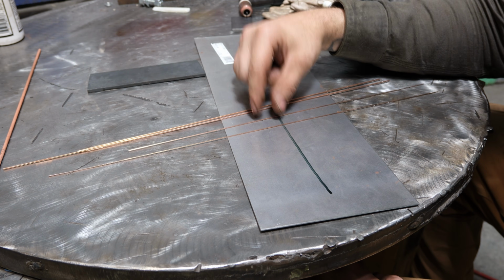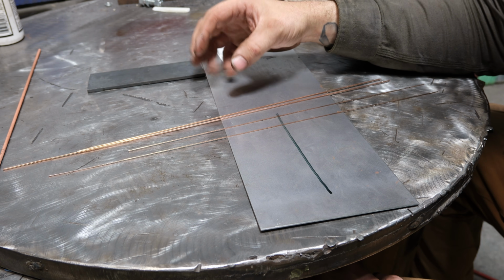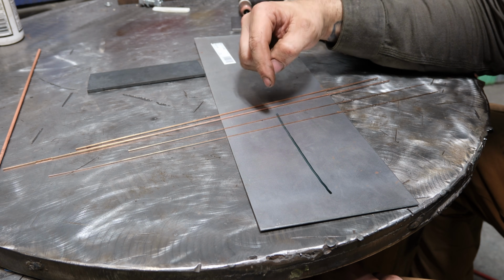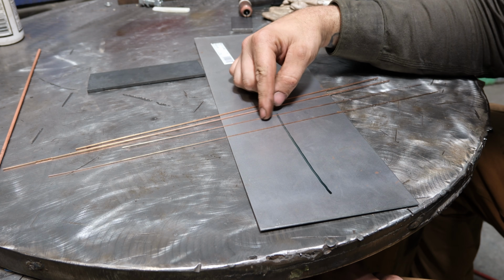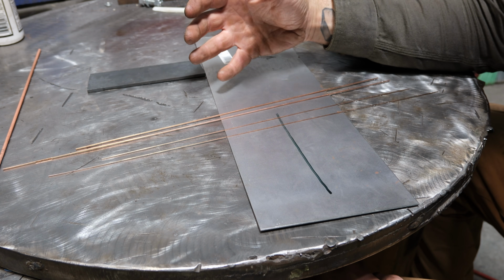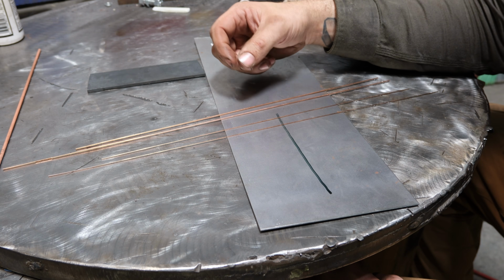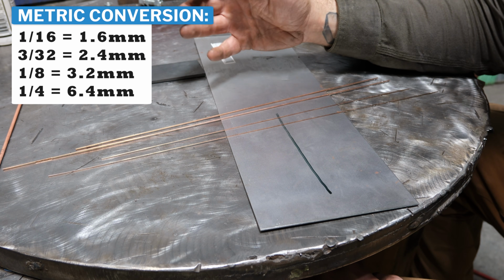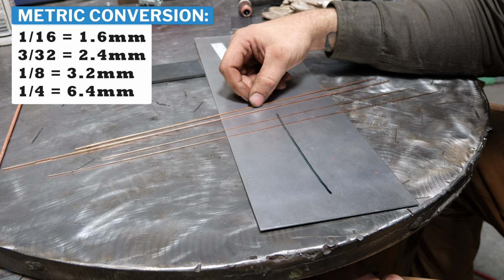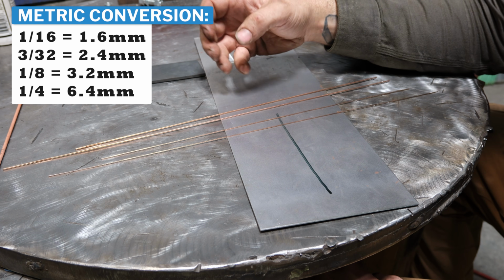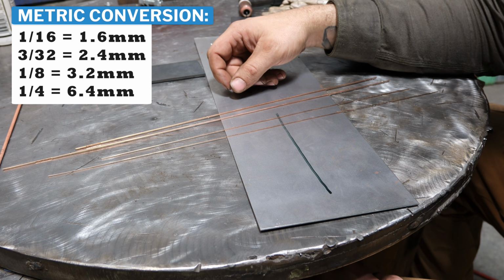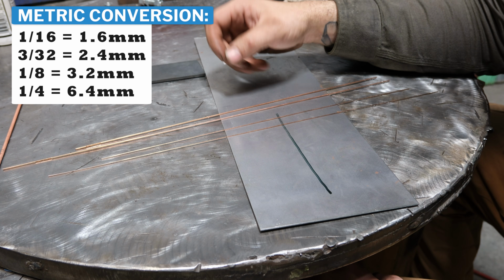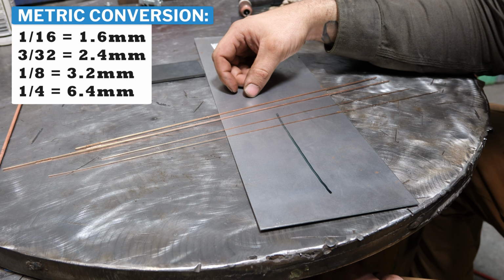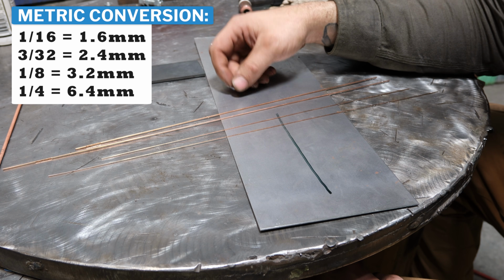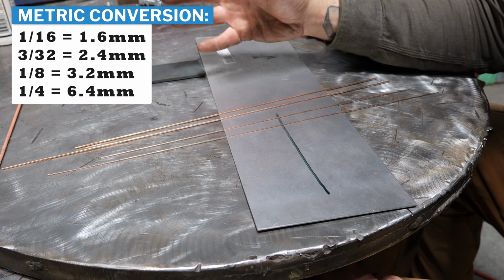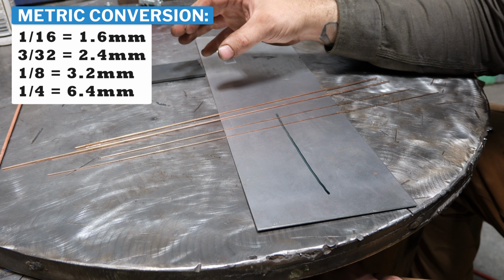Speaking of filler rods, one of the things I didn't understand when I was learning to TIG weld is the importance of picking the right filler rod. Now, when I was in school, they basically gave me 3/32 rod and said weld stuff. Well, the problem with that is 3/32 rods for steel takes a lot of amperage. You need to be well above 120 amps for just doing a bead on plate to get acceptable results with that, especially on a fillet weld. So I was basically running far too cold.